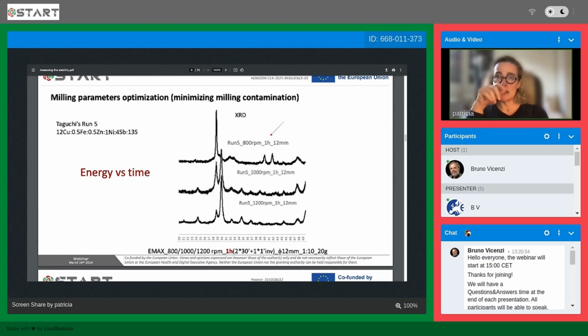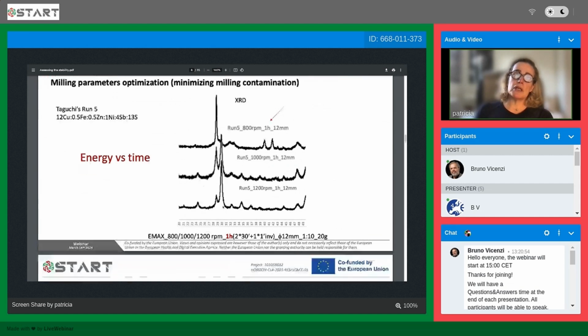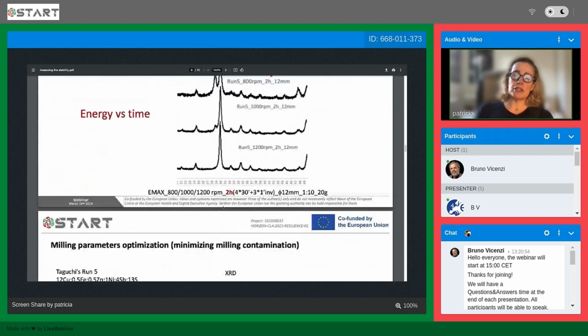And here we tested for 1 hour with balls of 12 millimeters. And you can see that only at 800 and 1,000 and even at 1,200 rotation per minute, with 1 hour, we still don't get only tetrahedrite, because this peak here, which is at around 28, 29, is another phase called famatinite. So 1 hour was clearly not enough.